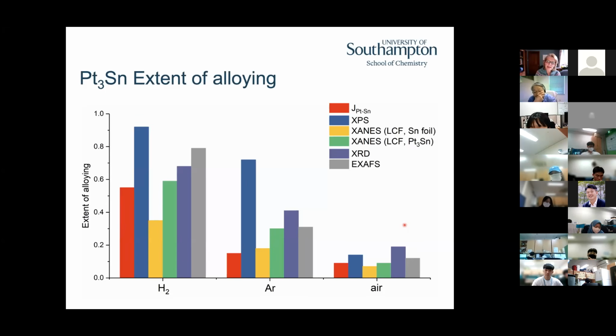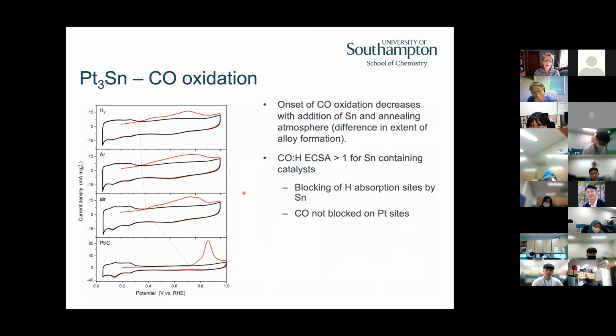So why would we be interested in platinum tin as an electrocatalyst? Well, it's interesting in the fuel cell environment for improving CO tolerance, but also as a catalyst to provide us with an active oxygen species in terms of, say, methanol, ethanol, or butanol oxidation. So if we look at the electrochemistry of our sample, this is a platinum and carbon reference material. Here are the CVs of those that were annealed in air, argon, and hydrogen. And this is the CO stripping voltammetry.